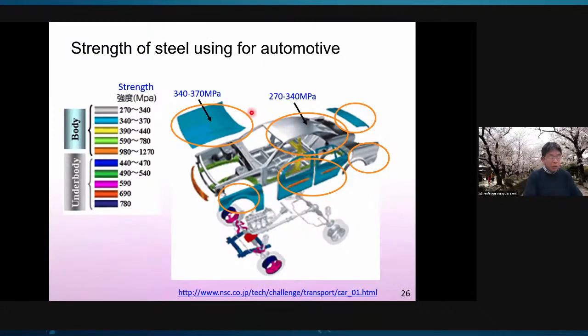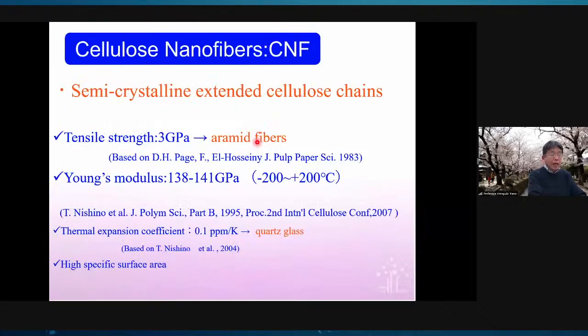The strength of steel used for automotive doors and the bonnet is around 300 to 400 megapascal. Cellulose nanofiber is more than 7 times stronger than steel, while its density is 1/5 of steel. The high strength of cellulose nanofiber is attributable to its semi-crystalline extended molecule chain structure. Because of this structure, CNF has high strength comparable to that of aramid fibers, as well as high rigidity.